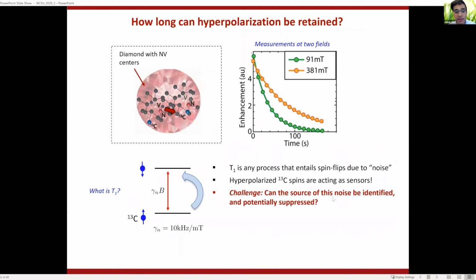The relaxation time of the nuclear spins can be very long. It's field dependent. This is what the slide is showing, but it's very, very long. It can be tens of minutes. The relaxation time of the NV electron is about a millisecond. This is roughly the time scale. But if you talk about the nuclear spins, this was a kind of surprise to us. If you just talk about a two-level system of nuclear spin, you can ask what is meant by relaxation. It is basically any process that can cause the spin to flip, right?